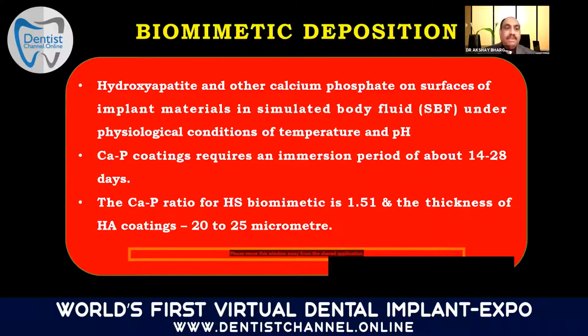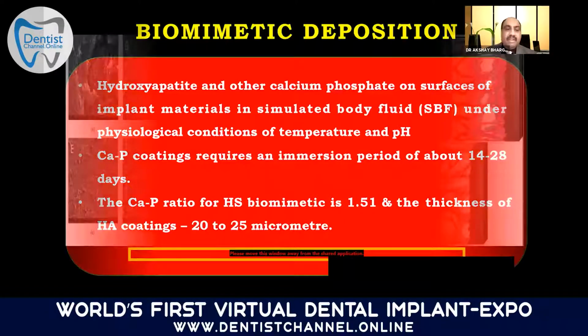Okay, that was nice. Now coming back to biomimetic deposition, you have hydroxyapatite and calcium phosphate on the surface, which basically involves placing implant materials in a simulated body fluid. So calcium phosphate coatings and hydroxyapatite in a thickness of 20 to 25 micrometers are placed. You again have a created rough surface. A small video to show you.